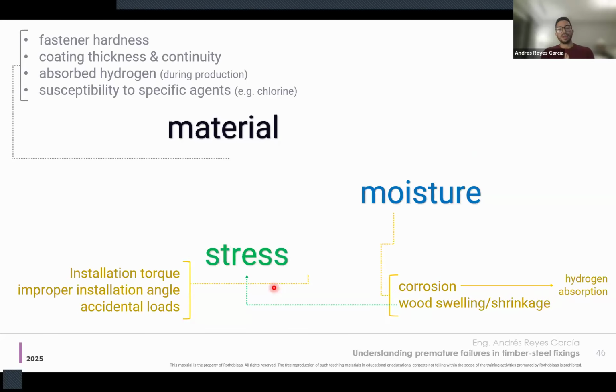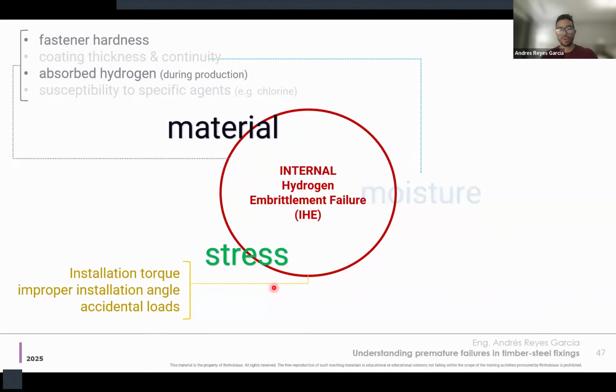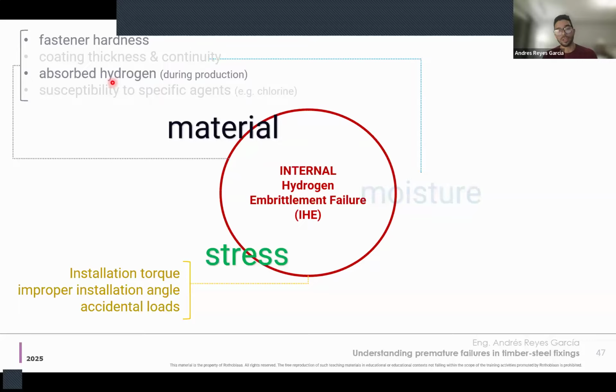So, back to the factors. We saw each one individually, but now we're going to talk about how they combine to produce premature failure. If we take moisture out of the picture, as we talked about at the beginning, and we have some unintended stressors like installation torque, improper angle, and accidental loads, combined with a material which is particularly hard and with some absorbed hydrogen during production, then we can have internal hydrogen embrittlement failure.